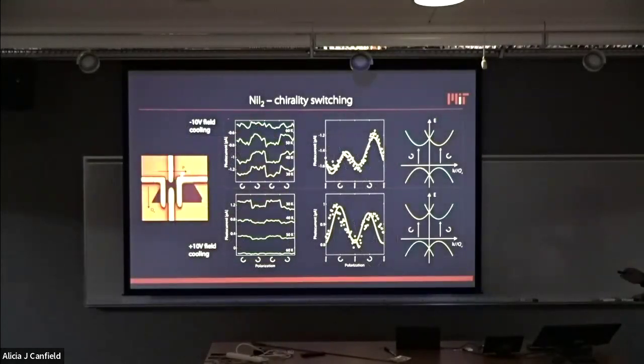So the catch here is that you have to polarize the material, but then you have to probe the photocurrent, the photogalvanic effect, in the direction which is along the helix, which is perpendicular to the polarization. And we see this very clear switching of the signal. So we have circular right and left, and we see this contrast between right and left. It's also very clear in these types of measurements here, as a function of the polarization angle. And that goes away at the transition temperature.